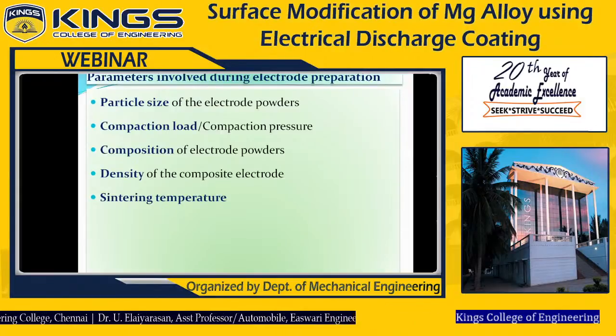No problem. Parameters involved during the electrode preparation. During the electrode preparation, there are some parameters: particle size, compaction load, composition, density, and sintering temperature. These are very important factors during the electrode preparation. If we increase the particle size, the compaction will differ. And then compaction load: while compacting the electrode, pressure is applied during the electrode preparation. And the composition is a very important factor. The proportion of the electrode powders, we can take it as a 50-50 ratio or a 70-30 ratio. The density of the composite electrode: based on the load applied during the electrode preparation, the density of the composite electrode will be controlled.